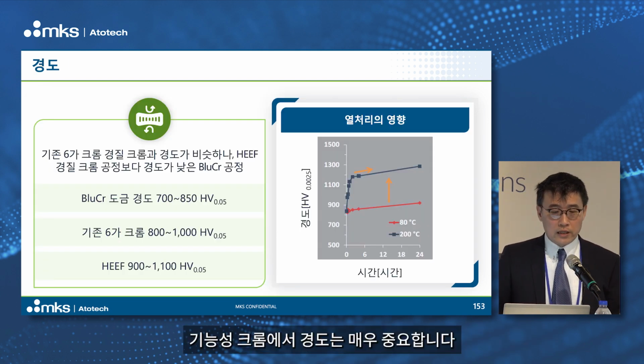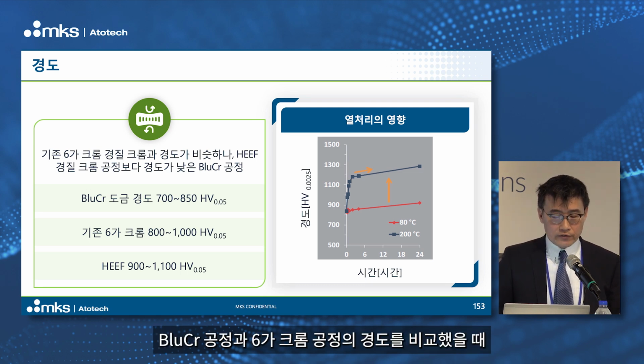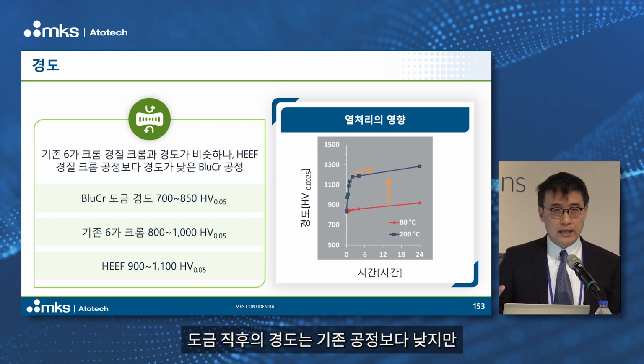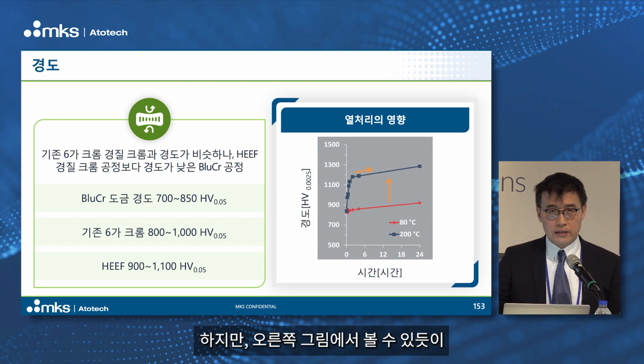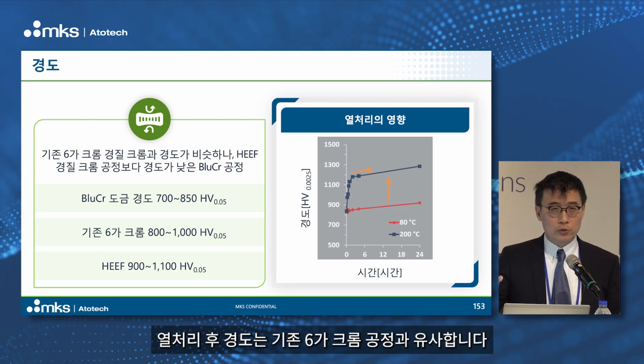For functional Chrome, of course, hardness is very important. When we compare the hardness of our BluCr process to the hexavalent Chrome process, the as-plated hardness is not as high as the traditional one. But you can see on the right-hand side, after heat treatment, the hardness is comparable to the normal Chromium 6 process.